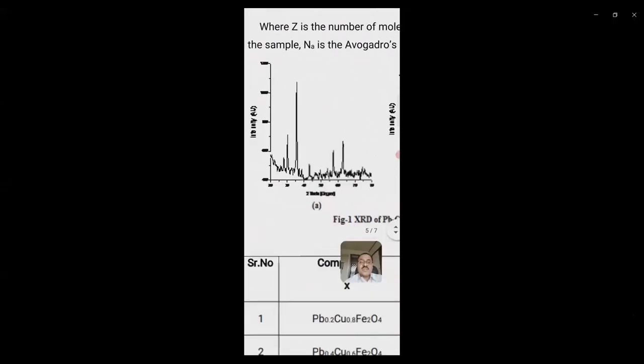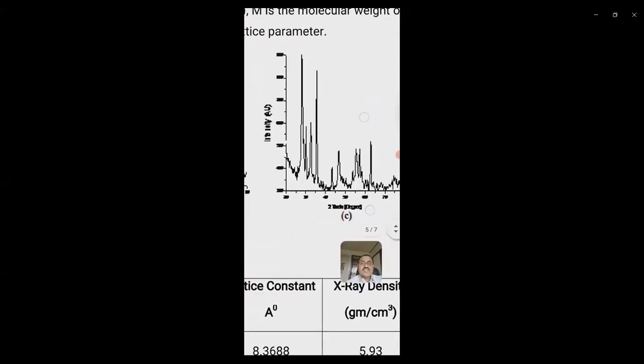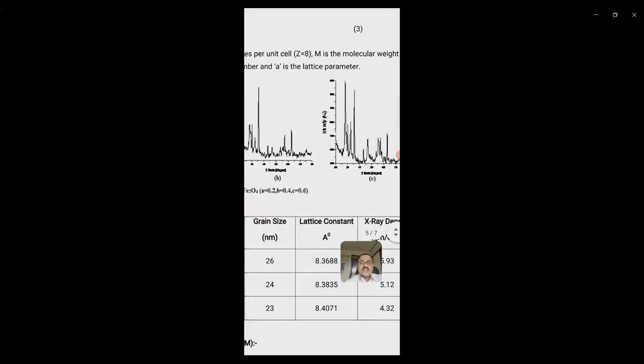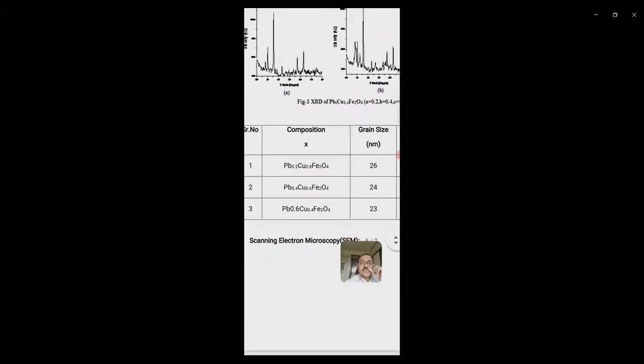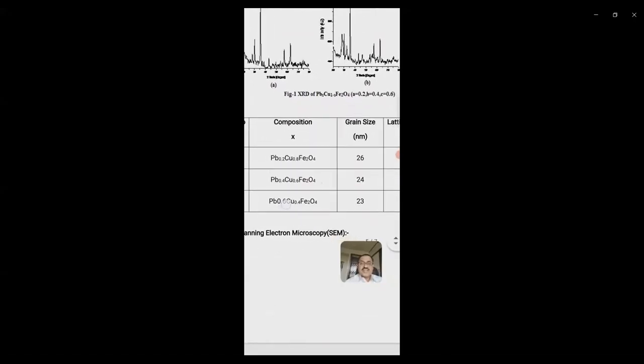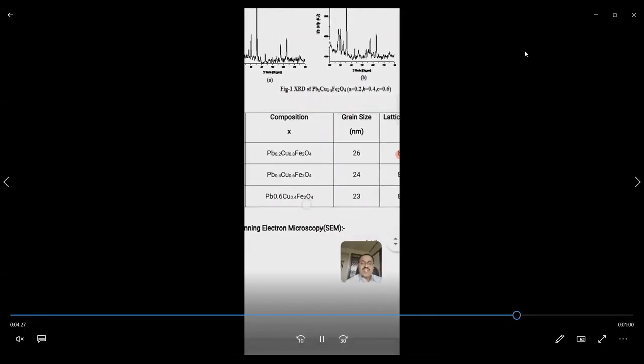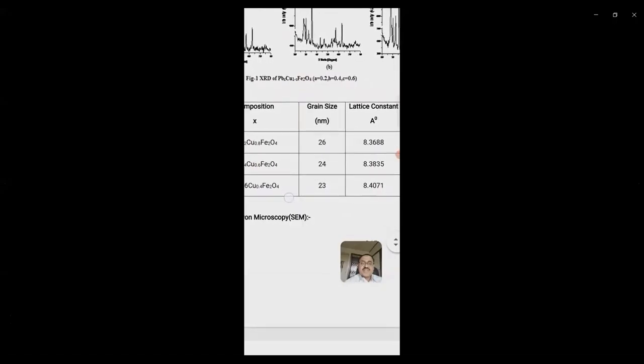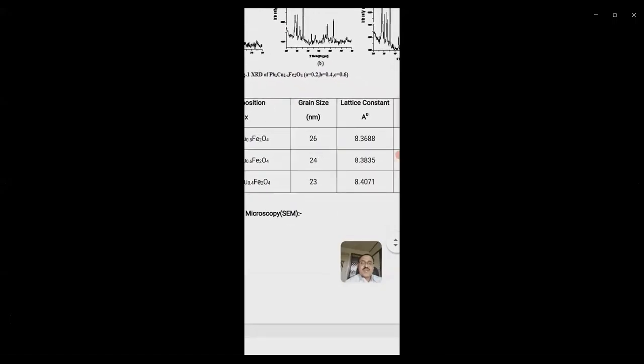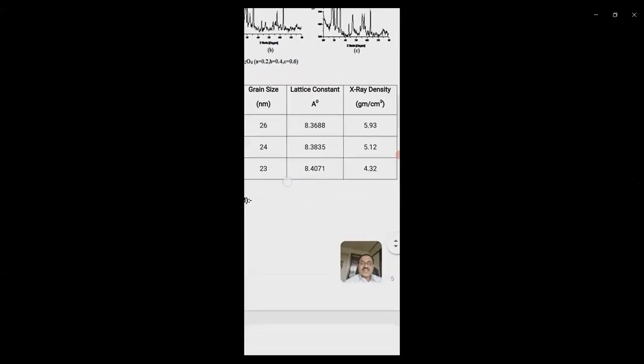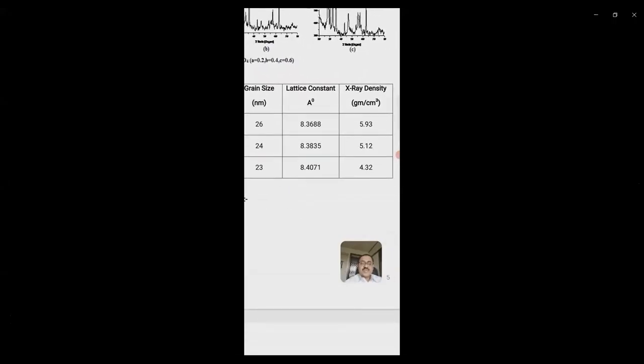So we get three X-ray patterns: for x equal to 0.2, this is x equal to 0.4, and this is x equal to 0.6. And these are the observed parameters for the three compositions, Pb 0.2, Pb 0.4, and Pb 0.6. The grain size was observed with increasing x value. The grain size decreased from 26 nanometer to 23 nanometer. Lattice parameter was increasing from 8.36 to 8.40 angstrom. X-ray density was decreased from 5.93 to 4.32.